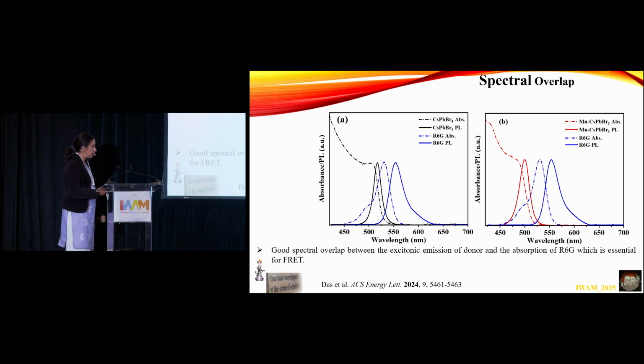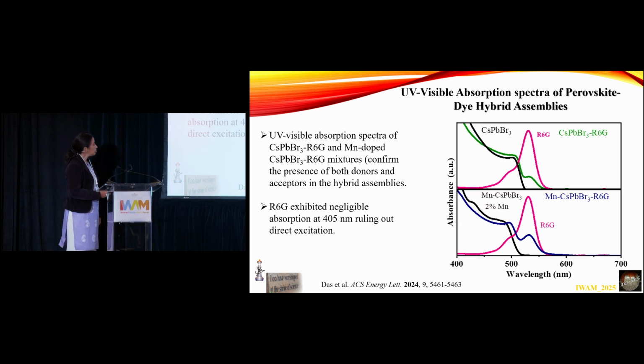excited state. These are just normal bookkeeping to make sure that there is a good spectral overlap of the donor and the acceptor, and you can see that R6G is indeed overlapping very strongly, both in case of doped and undoped. So now my question is whether the transfer efficiency changes as a function of doping or not? So this is what we did.